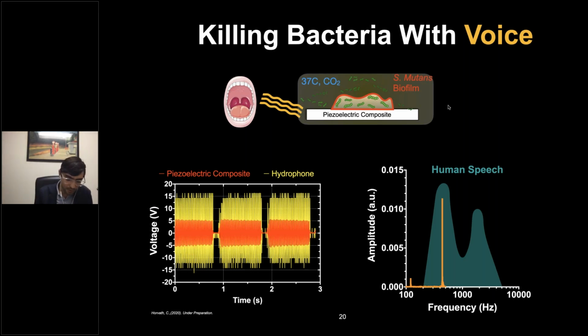First thing we did was measure if indeed some acoustic signal we sent are around 450 hertz, which is kind of the peak found in human speech. So we simplified the method by just getting one sound at the peak frequency, then we put it in the liquid culture, put a hydrophone and our material, and we were measuring how much charge or voltage we were getting.